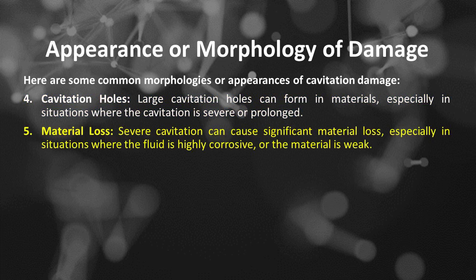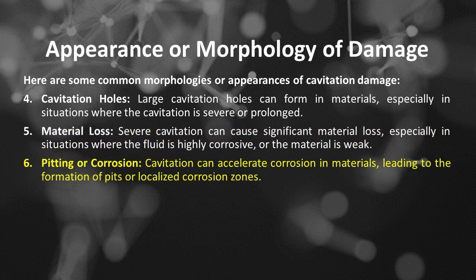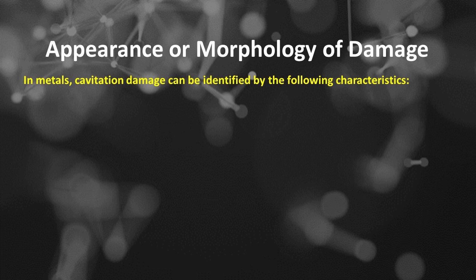Number 5 is material loss. Severe cavitation can cause significant material loss, especially in situations where the fluid is highly corrosive or the material is weak. Number 6 is pitting or corrosion. Cavitation can accelerate corrosion in materials, leading to the formation of pits or localized corrosion zones. In metals, cavitation damage can be identified by the following characteristics.